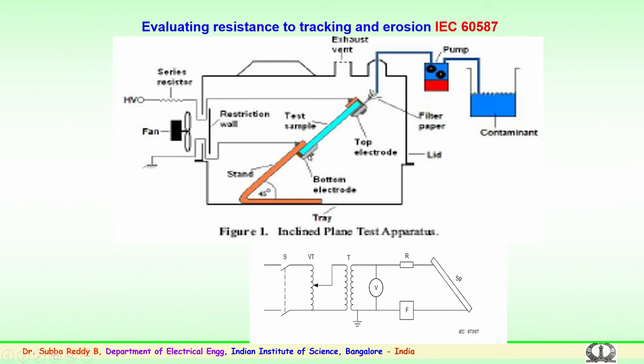The test sample is here, this is the bottom electrode, this is the top electrode, and the top electrode is connected to a peristaltic pump, where the water droplets at regular intervals have to be in contact, where the water droplets go on the surface of this insulator sample, and the high voltage is applied between the high voltage top electrode and the bottom. The voltage, again it is known, either 3.5 kV or 4.5 kV as per the standard information. So this is how the arrangement is to be made for studying the inclined plane experimentation for both AC and DC application. The standard very clearly specifies for AC application.